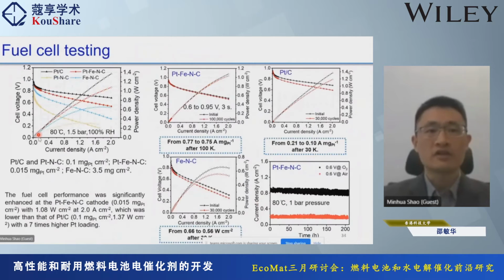Okay, and then fuel cell testing. You can see that the black is the platinum benchmark, and the red one is our platinum iron nitrogen hybrid catalyst. So you can see the performance is already very close to the benchmark platinum, but the platinum loading is much lower. For platinum it is 0.1 milligram per square centimeter, for the hybrid it is only 0.015. Okay, so it's 7 times lower.